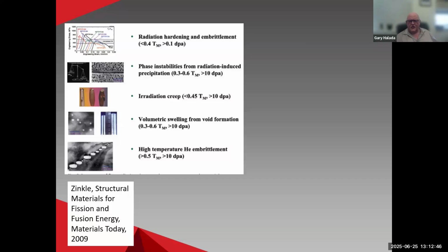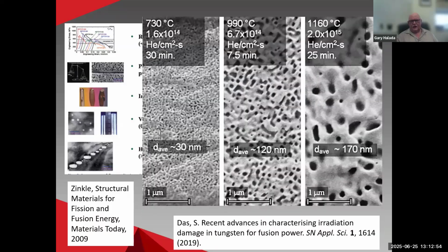You can also get the formation of voids because you get gas generation from irradiation of certain materials, and so forth. You can see that, for example, this was looking at irradiation damage in tungsten. Tungsten's a really good material for a lot of applications, a very strong, very durable material. However, under high temperatures and irradiation, you can see the formation of voids that become larger with time in the material, which can lead to failure.